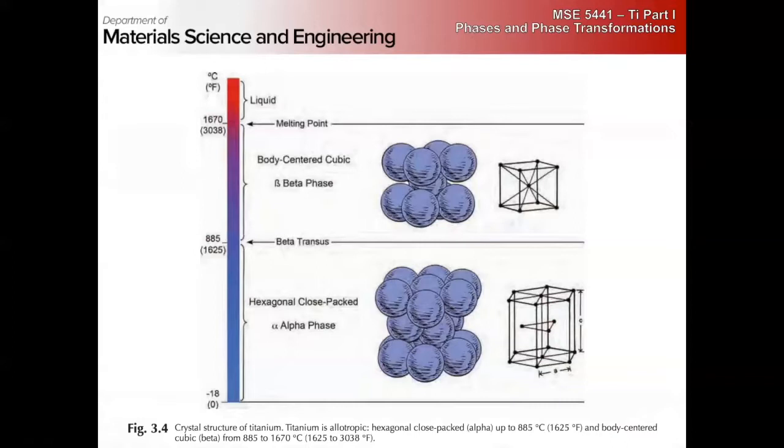A really cool thing, I don't have it here, but they also have high pressure phases that stick around. So regular alpha titanium, commercially pure grade 2 titanium is all HCP. If you heat it up, you transform to beta phase, which is BCC, so another lower symmetry.